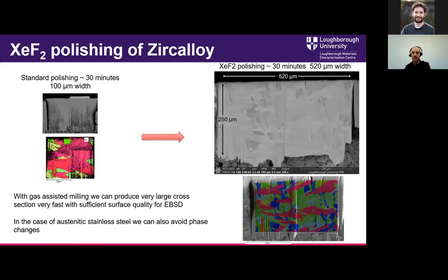However, by using that GIS needle, we can flow xenon difluoride into the chamber, and this increases the sputter yield of the material, and allows us to cut at high currents without getting curtaining effects. And so you can see for a comparable period of time, so around 30 minutes, we can get a significantly larger area cut, up to 520 microns width and 250 microns deep. And as I was saying before about statistical significance, with tricks like this, we can go from something that isn't really statistically relevant, where we've just got 5 grains, to something that is more statistically relevant, an area with around 300 grains. So something we can do some analysis on.